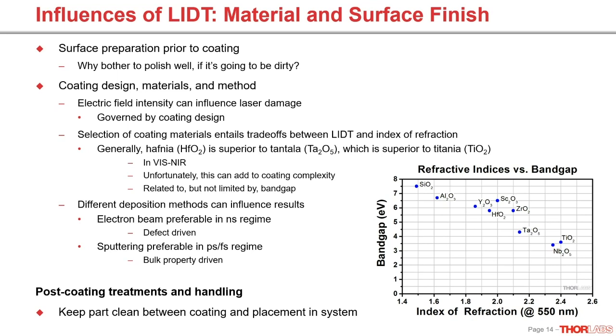Or if you have a peak in one of the higher index materials, that's also going to be a problem. So if you can manipulate your electric field to peak in the lower index layers, or, as I'm going to get into shortly, the layer with the better band gap, you're going to have better results. And if you look in the literature, you can see this can be an order of magnitude, which is obviously very significant.